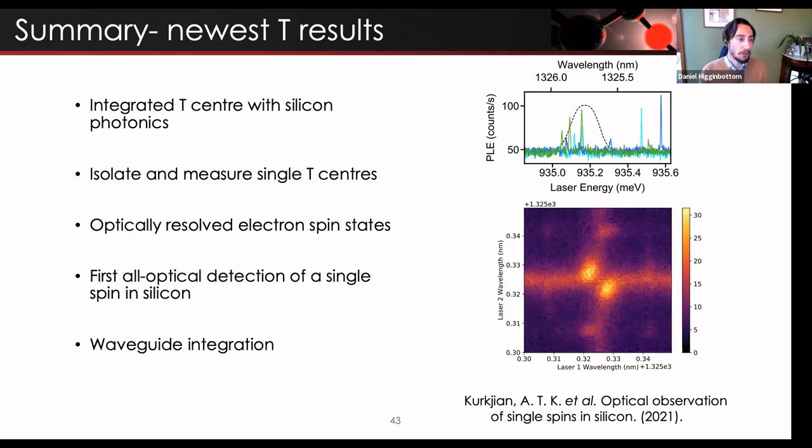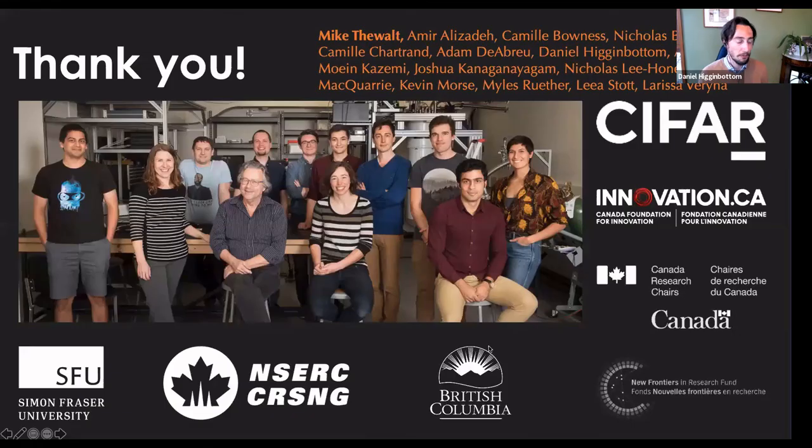The particular results that I wanted to highlight are with integrated T centers with silicon photonics: we've isolated and measured single T centers, we've optically resolved the electron spin states, we've done the first all optical detection of a single spin in silicon, and we've further demonstrated integration with waveguides, which is the next step to useful circuits.